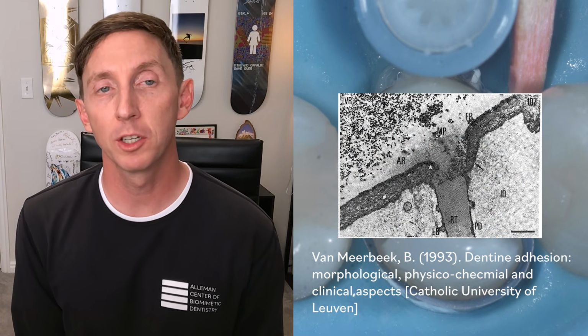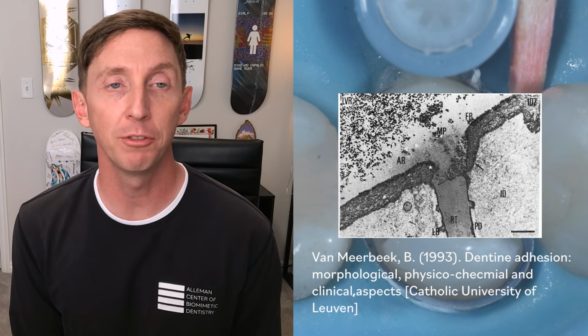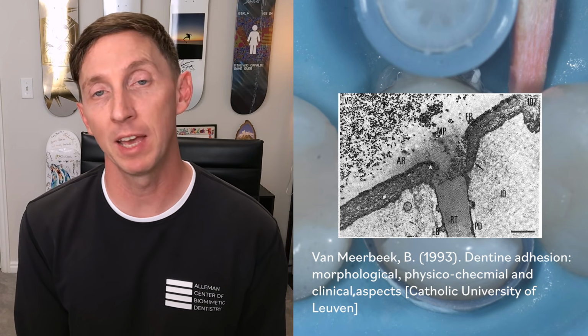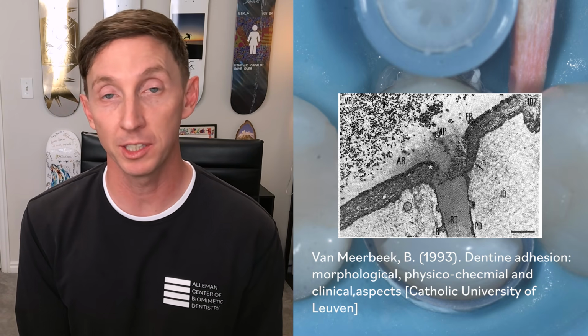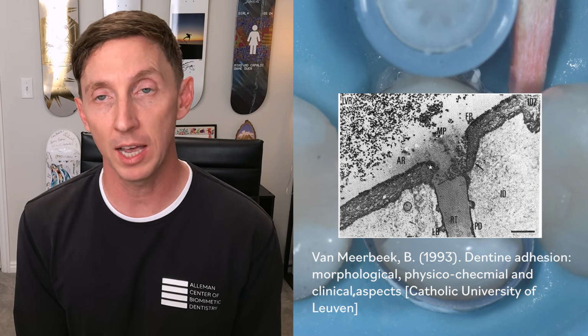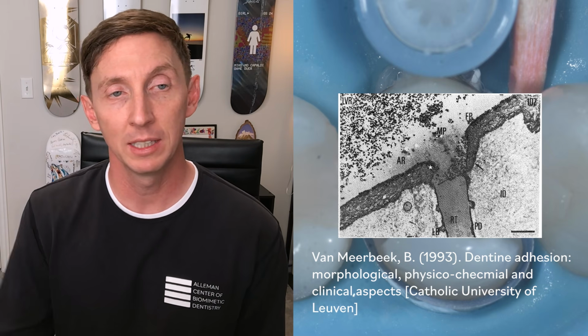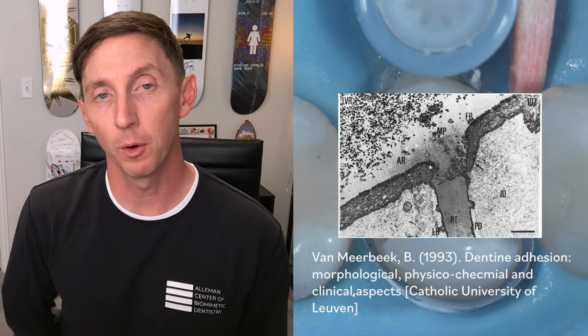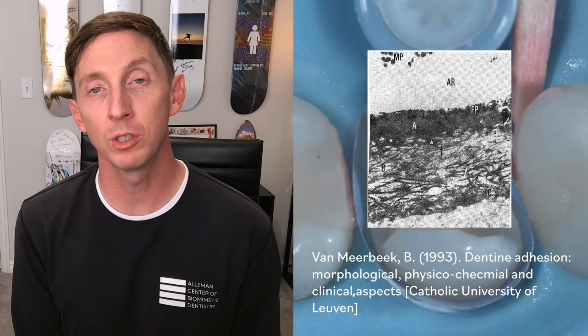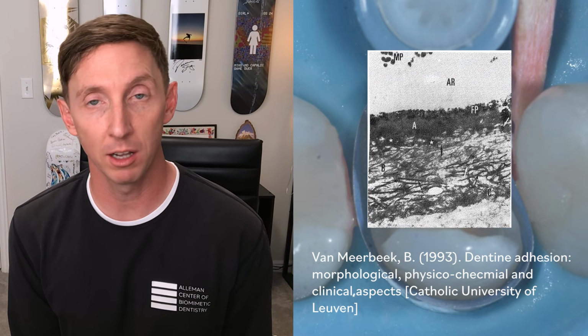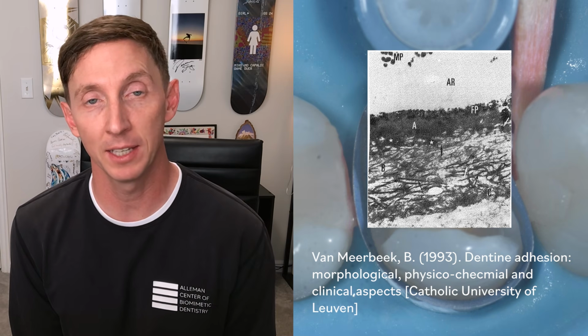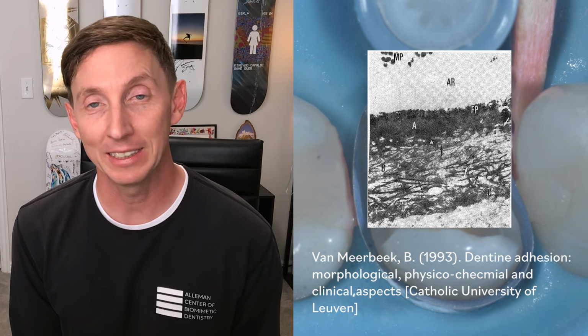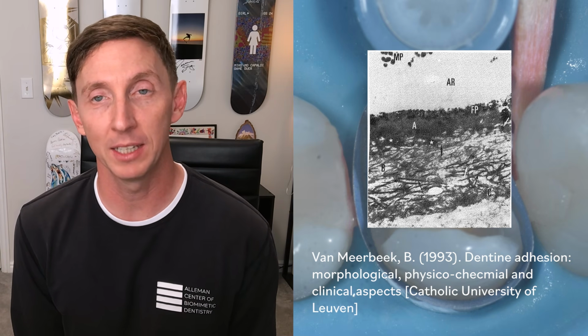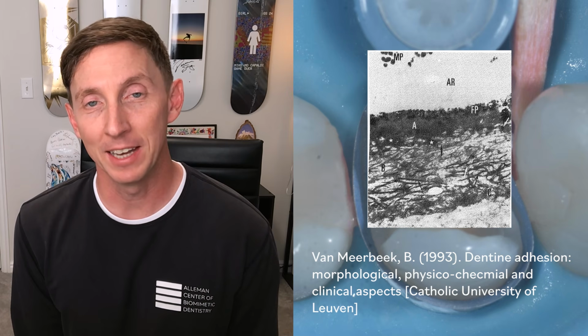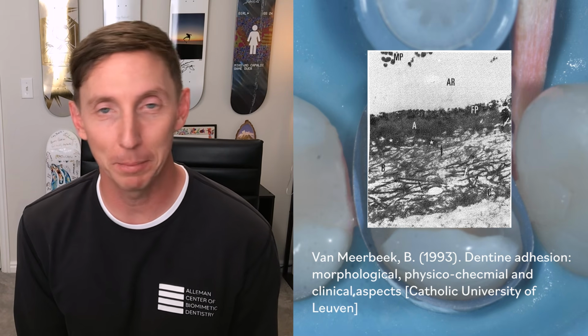The hybrid layer could be described as an interdiffusion zone. And in fact, Bart Van Meerbeek in his PhD dissertation in 1993 described the hybrid layer in these different areas. That there are 4 interdiffusion zones. Now, the top layer is mostly collagen with some hydroxyapatite. The next layer has equal amounts of hydroxyapatite, collagen, and water. And the next layer, mostly hydroxyapatite and collagen, and the bottom layer is sound dentin.